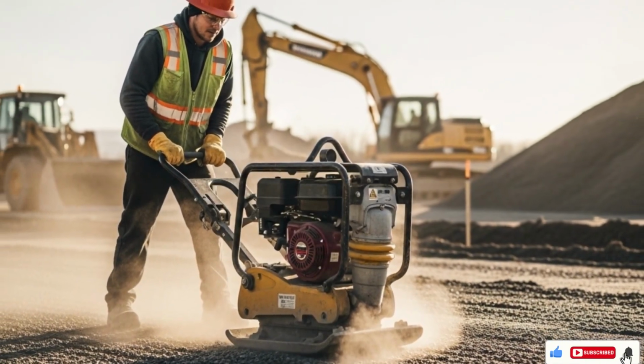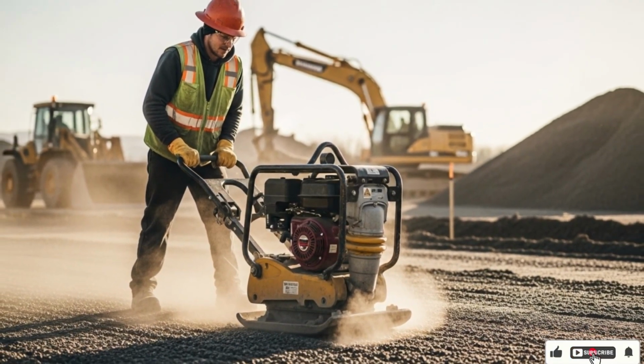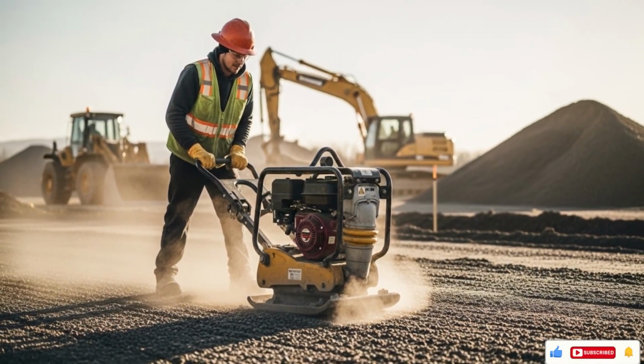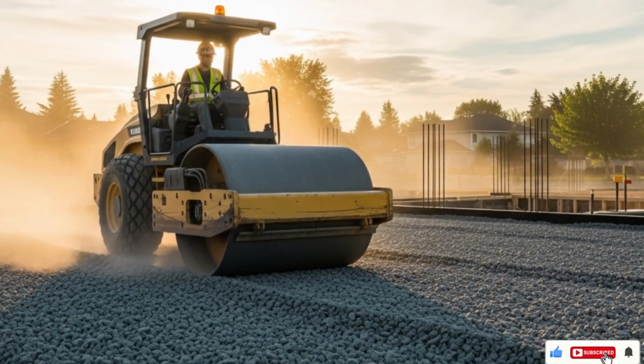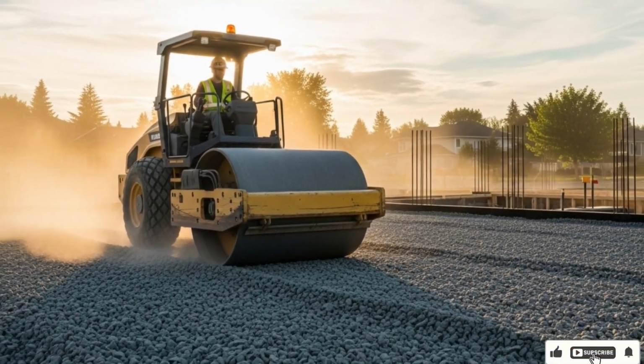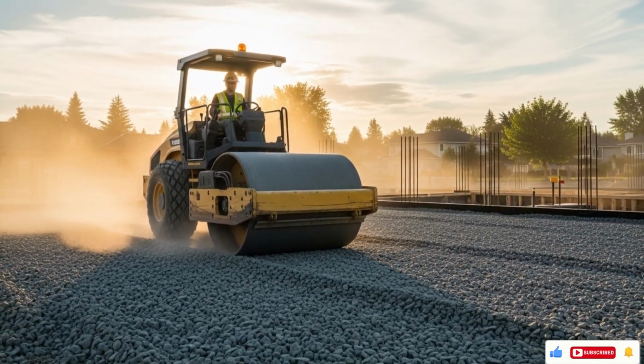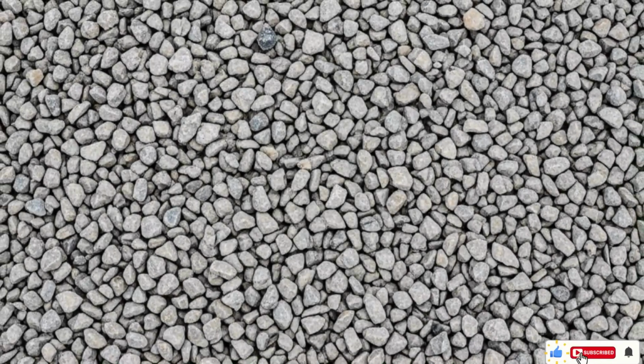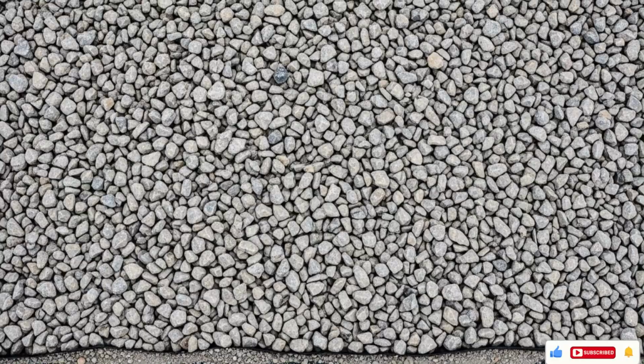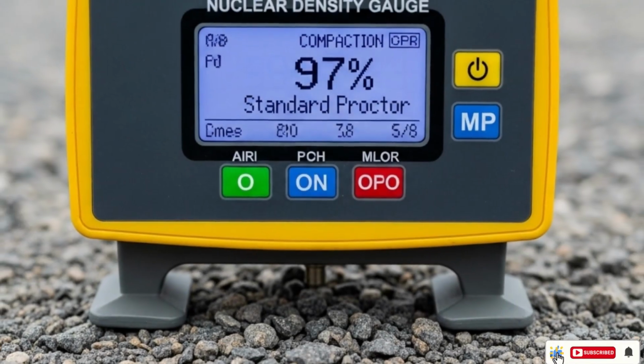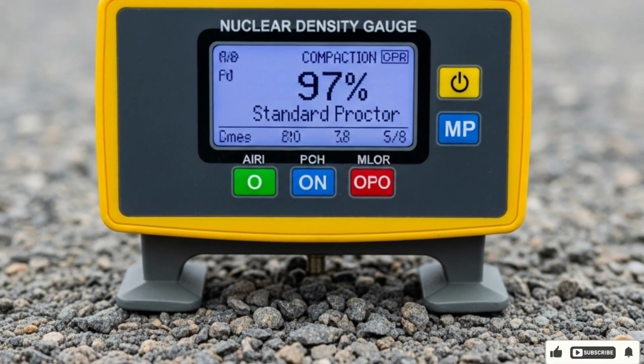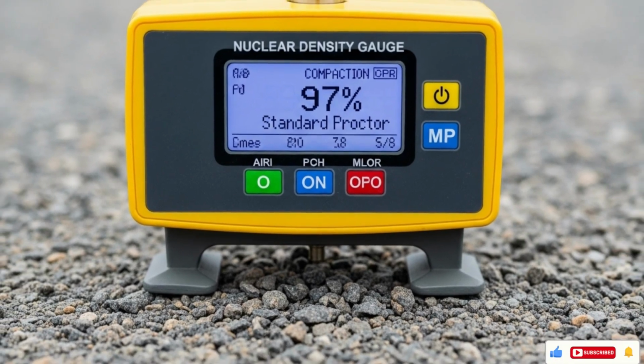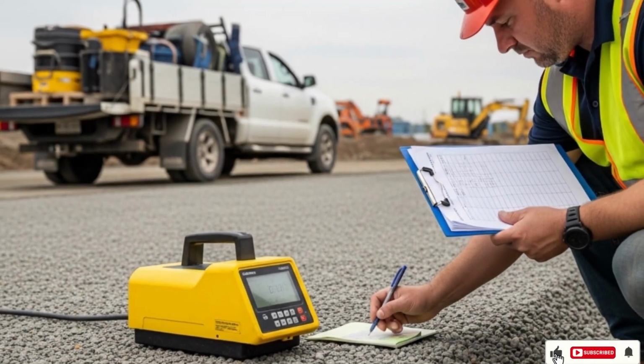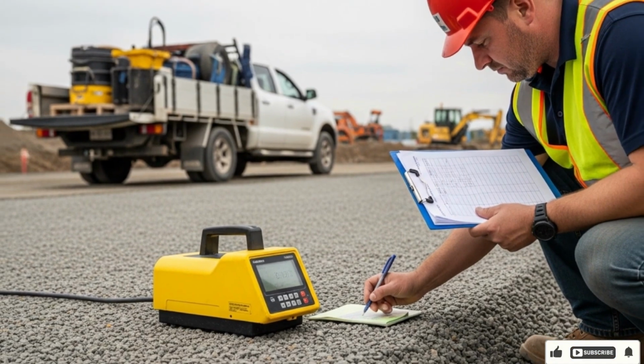The subbase performs 3 critical functions. It provides a uniform, stable working platform for all subsequent operations. It improves drainage beneath the slab, directing water away from the base of the concrete, and it interrupts the capillary rise of moisture from the soil below, the natural tendency of water to wick upward through fine soil particles toward the underside of the slab. Compaction must be verified to a minimum 95% standard Proctor density, not estimated visually but tested by a materials laboratory.